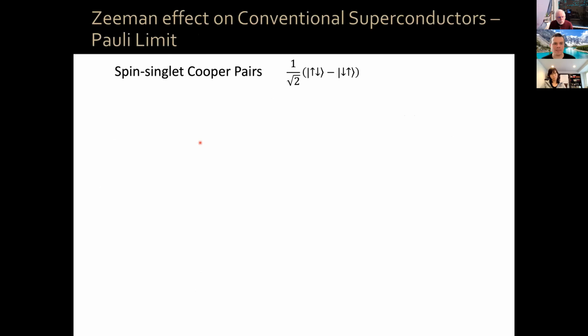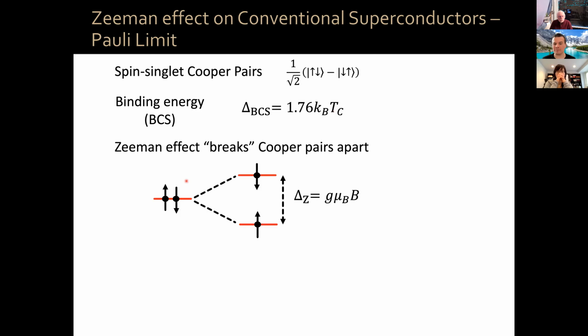So now, what is the usual Zeeman effect on conventional superconductors? Well, conventional superconductors have spin-singlet Cooper pairs, okay, shown here. The binding energy of these Cooper pairs is given by the gap, which is 1.76 times kBTC. That's within the BCS theory of superconductivity. And Zeeman field breaks apart or splits those spins, such that when the Zeeman splitting, which is gμBB, is equal to the superconducting gap, then superconductivity should be suppressed.